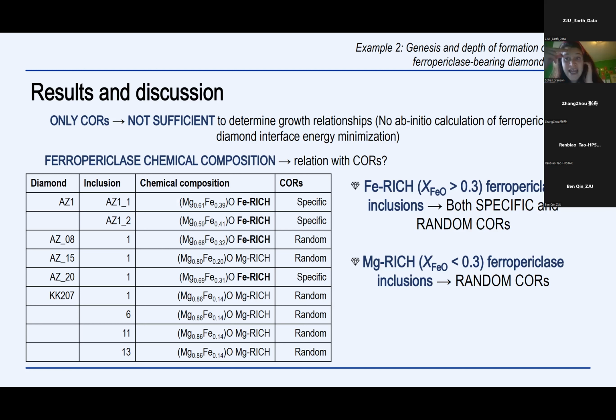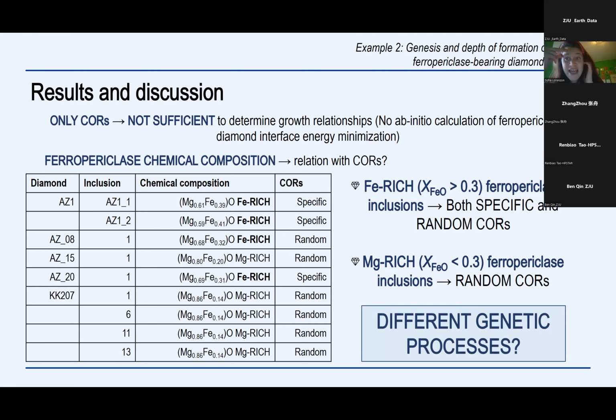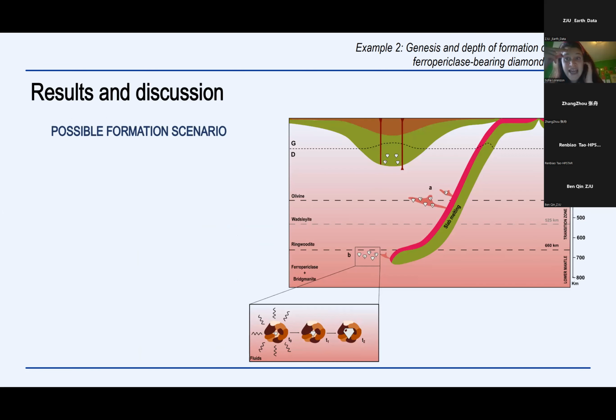for the COR determination. And we obtained that the iron-rich ferropericlase inclusions present, in most cases, specific CORs. Only one case presents a random COR. On the other hand, the magnesium-rich ferropericlase inclusions present random CORs in all cases. And this leads us to suppose that ferropericlase inclusions within diamonds with different chemistry can have different origins in the Earth's mantle. And consequently, we suppose two different formation scenarios for ferropericlase-bearing diamonds in the Earth's mantle.